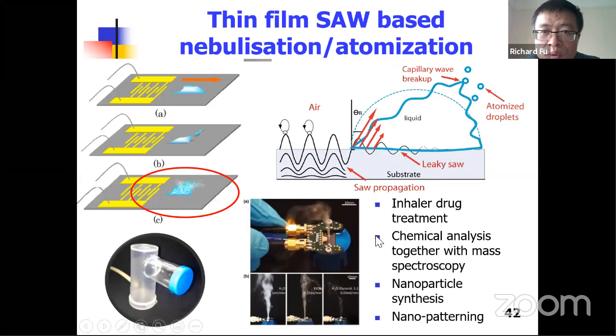Another phenomenon related to the surface acoustic wave thin film device is called nebulisation or atomization. In this case, the surface is hydrophilic. The droplet won't move away quickly, but stays there. But there is significant wave agitation on the surface, called capillary wave. If the amplitude increases too much, very tiny droplets are ejected, forming a kind of mist. This mist can be used for nanoparticle synthesis or even for cell collection, because you can quickly move a glass slide over this mist and pick up a layer of nanoparticles or biological cells. People also use it for drug inhaler applications.